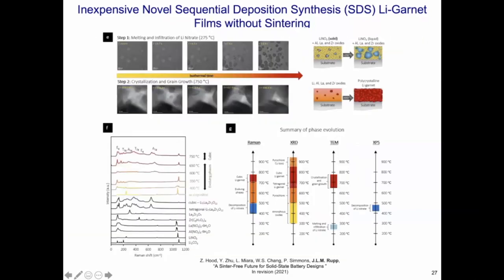Now, what I also want to show here is a little bit more about the formation. So in this particular case, I go back to my favorite Raman spectroscopy, because I love to look really into the near order and what's happening with the lithium and oxygen vibrational modes and also many others of the light elements. So what's exciting is that in the beginning, when we deposit at around 200, 300 degrees C, we form a glass-like dense film. And in the film, we can show actually in Raman spectroscopy that the lithium salt, which is a lithium nitrate, is even trackable in the beginning of the film.